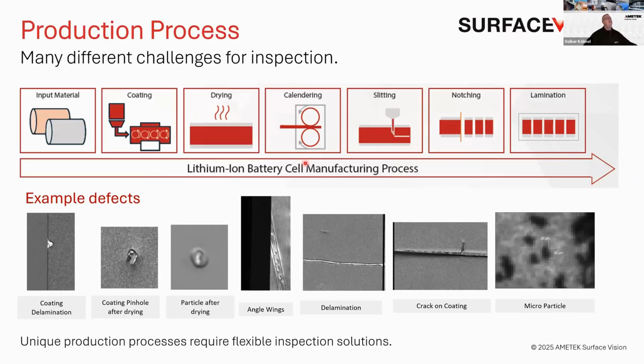Then on the calendering process, there's a slightly different request for the inspection system when it comes to speed, when it comes to maybe different type of defects. So one example, it's here on the collector, it's outside the coating, when the calendering process is not well processed, that you generate kind of wrinkles on the edge. So some customers call this angel wings. So this is an indication that the calendering process has issues. Beside that, you have to inspect the coated area as well to see if you add any other kind of pinholes coming after the calendering process. And then on the slitting, you are more focusing on the edge of the slit, edge burrs and so on.